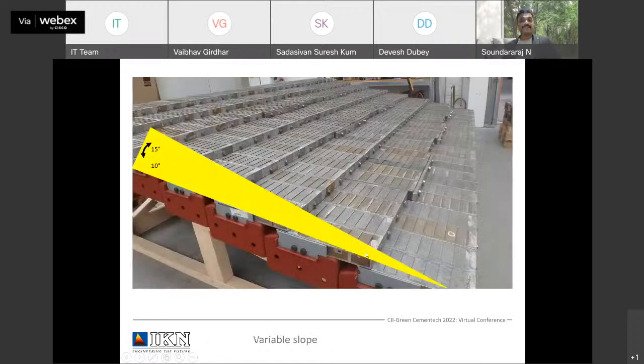So the next important thing is the finer clinker. How to handle the finer clinker? You can change the slope of the grate now. Earlier it was a fixed slope of 15 degrees. Now you can change it up to 10 degrees. So a lower slope provides better cover for the upper grate surface area and a lower risk of fines getting blown off. So always more material on the grate, you can give strong aeration and it will be quicker quenching and also better recuperation.